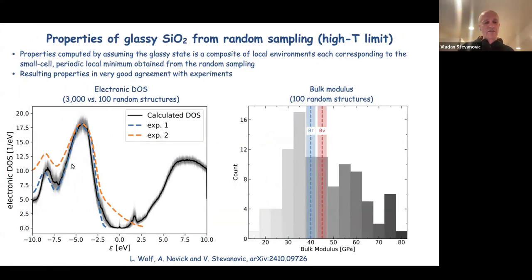This is the black curve on the left, and then the two experimental results that we found in the literature, both UPS photoemission measurements done sometime in the 70s at TJ Watson, IBM labs. Again, the correspondence of our average result with experiments is fairly good, or at least within the differences that you find in the literature between different experiments. This is a very interesting result because you could, in principle, now imagine calculating electronic structure of disordered systems in general through this collection of small cell local minima, which would then enable high accuracy electronic structure calculations.